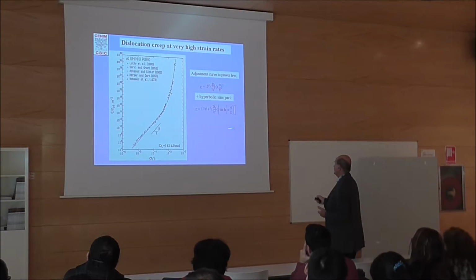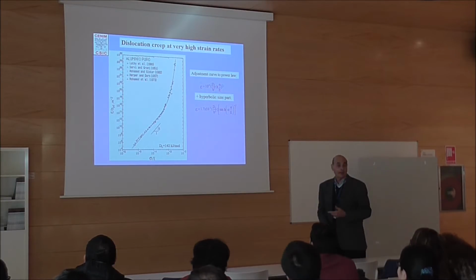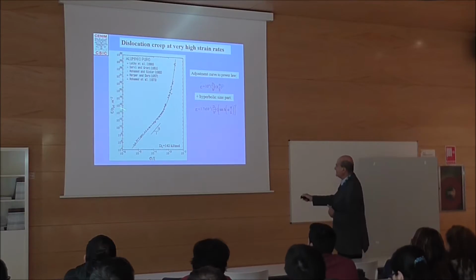If you use this hyperbolic sine part, you see that everything correlates very, very nicely in pure aluminum and in others, 27 orders of magnitude, strain rate compensating.